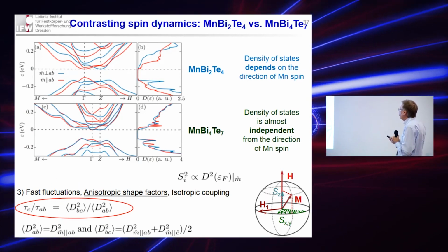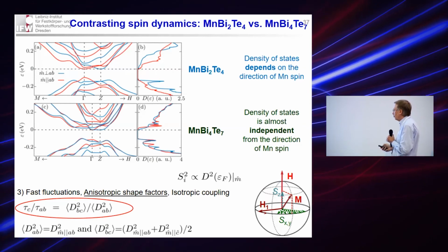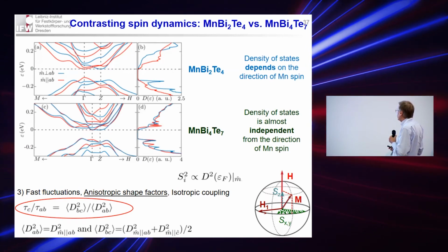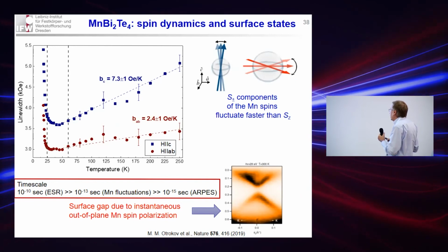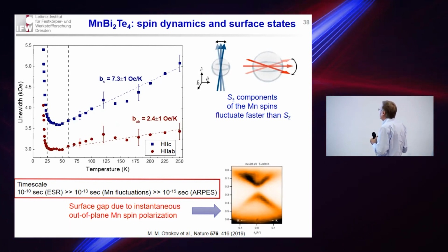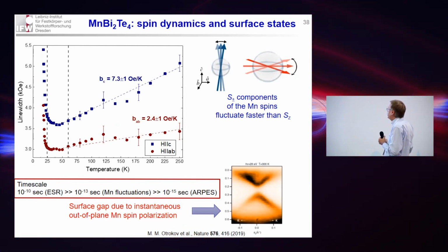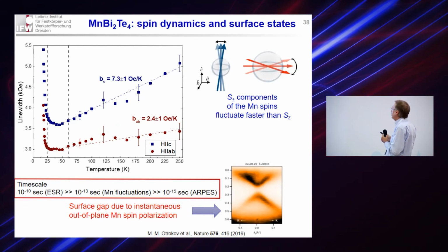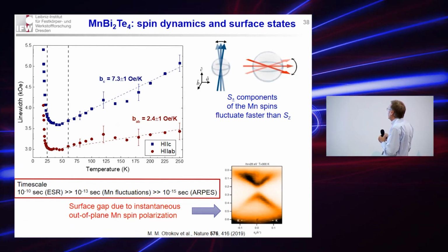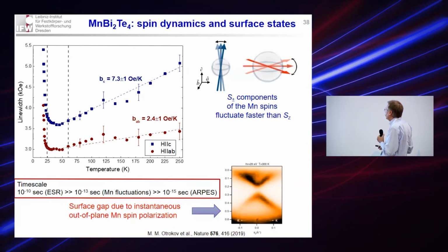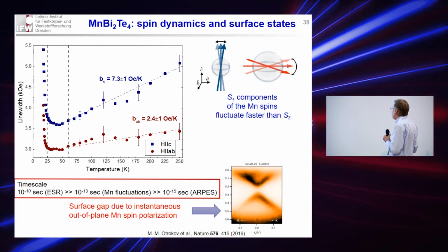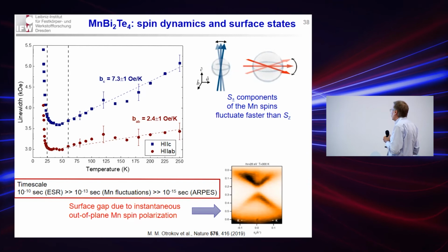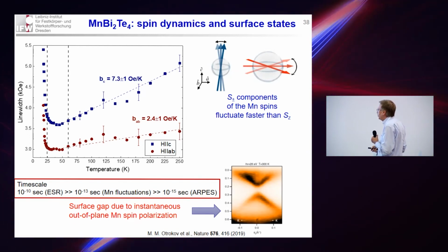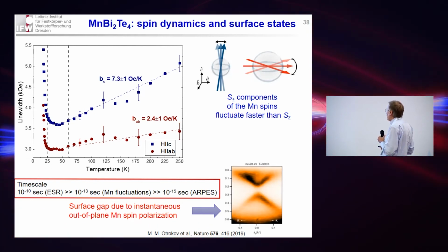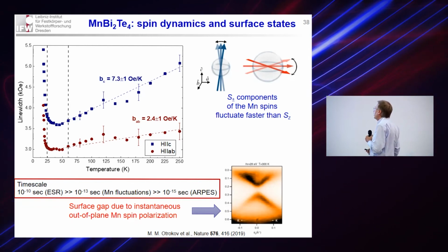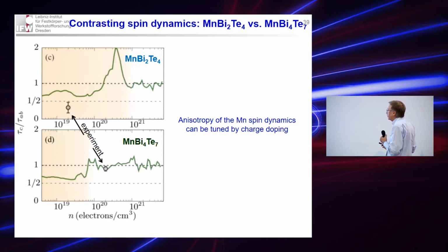And this anisotropy causes the anisotropy of the fluctuation rates of the manganese spins due to the anisotropic relaxation on conduction electrons. Therefore one can make a very simple picture of the bulk manganese spins fluctuating anisotropically in the paramagnetic state. They generate some kind of instantaneous out-of-plane magnetization, because the fluctuation along the c-axis is much smaller than in the plane, as is shown by different slopes of these relaxation curves. And that could be an important reason for the observation of the non-vanishing gap or pseudo-gap in the Dirac cone also above the ordering temperature, because, considering the time scale of the ARPES experiments, this fluctuation could be quasi-static.